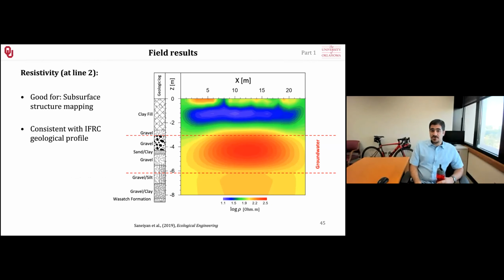Resistivity clearly showed the subsurface structure. Obviously, as we all know, we were able to see everything with resistivity, but it wasn't the right signal for calcite precipitation. I'll show you in the next slide. We were able to see the clay layer that was put in that site as a part of site remediation in the 1990s. We were seeing the groundwater region in the porous material with a higher resistivity because that was fresh water. So electrical resistivity was really good for mapping the structure.